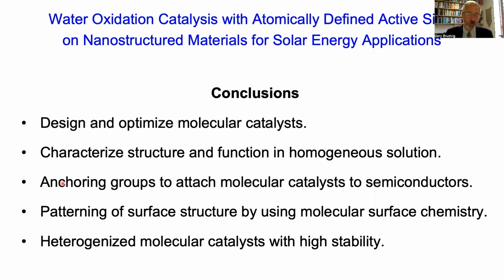And then we can use anchoring groups to attach the catalyst to the surface of metal oxide materials. And in the case of the silatrane anchoring group, we can use it for patterning the surface to use molecular surface chemistry to attach, for example, dyes and catalysts in adjacent proximity. And then once we've attached these molecular catalysts to the surface, we have extremely stable systems which can carry out light-driven water oxidation for many hundreds of thousands or millions of turnovers even, without degradation. And so I think this is really an exciting direction for the future, for combining the strength of molecular chemistry with the stability and efficiency of heterogenized catalysts.